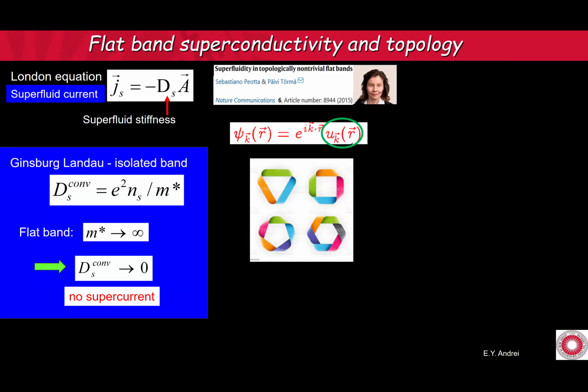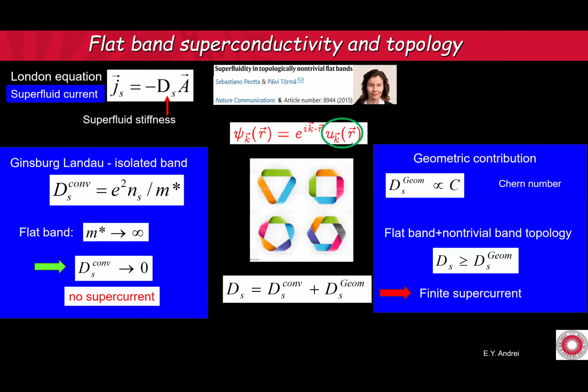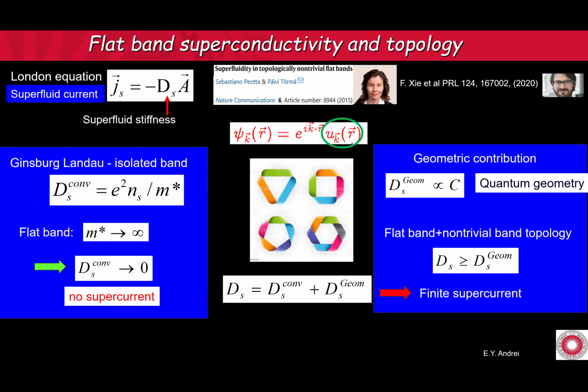So to the rescue came another Finnish group, Päivi Törmä here, and she realized that there is a way out. If your wave function has a non-trivial geometry, then she calculated that there is an additional term in the superfluid stiffness, which is a geometrical term. And she showed in 2015 that this geometrical term is proportional to the Chern number. And in that case, you have a lower bound, and you can get supercurrent. A few years later, Andrei Bernevig showed that this is a much less restricted condition. It's enough to have quantum geometry, a Berry phase or quantum geometry in general.